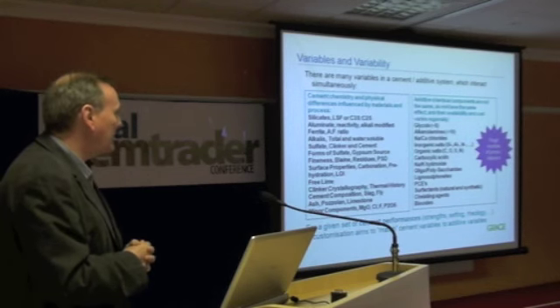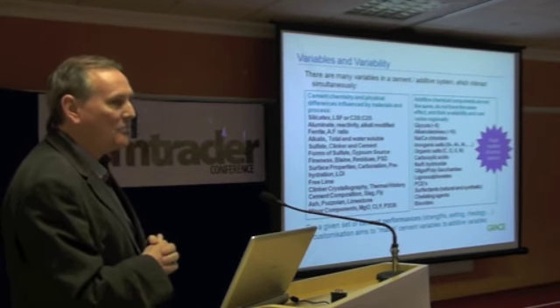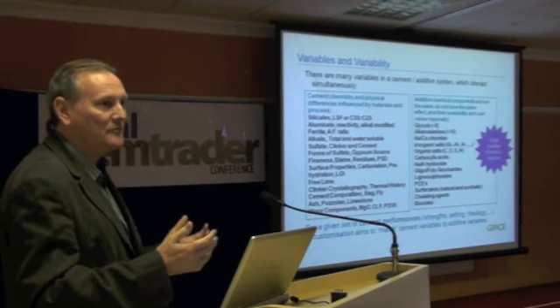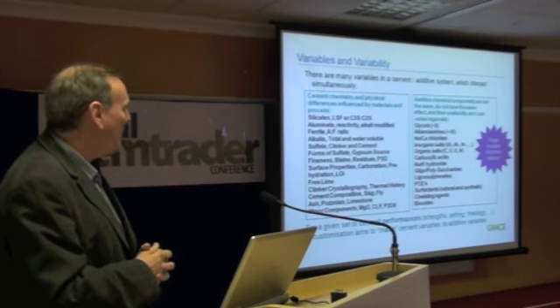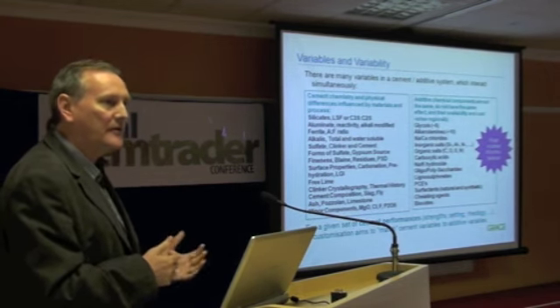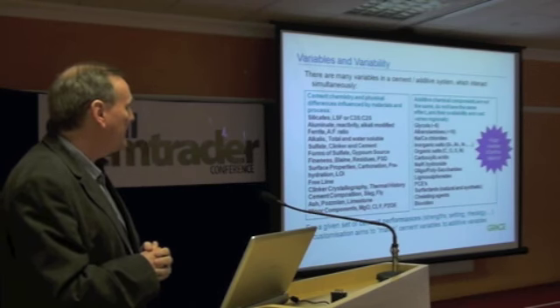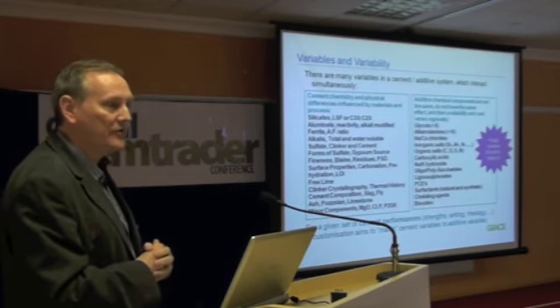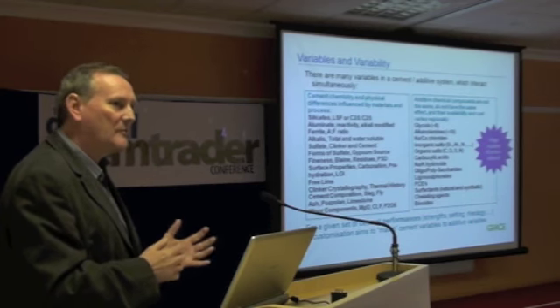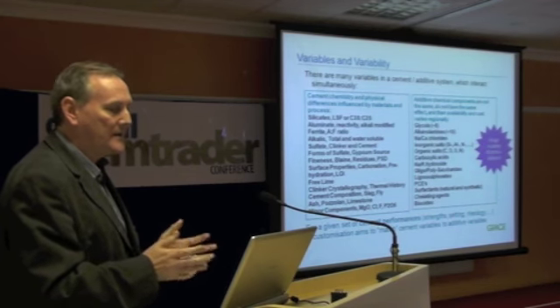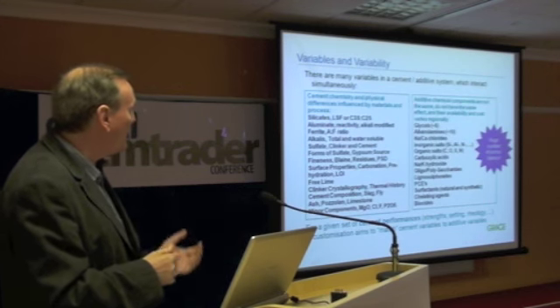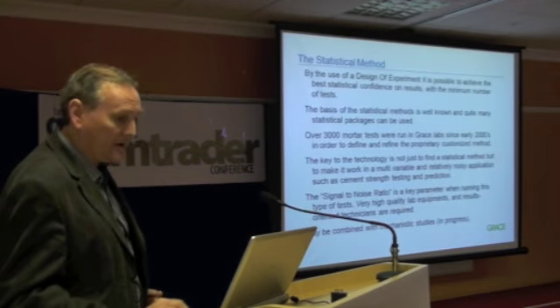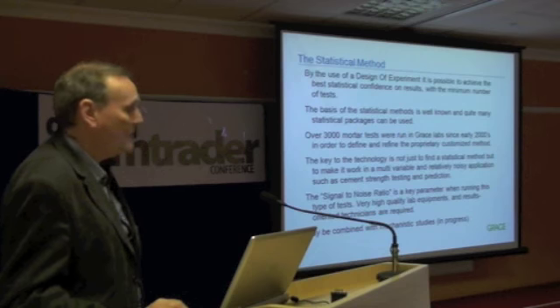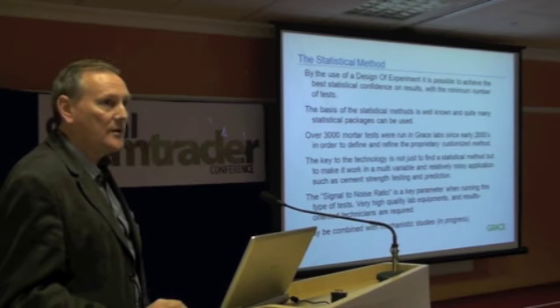So you can say that we have a bit of a practical trial and error approach, which is true to some extent, but combining a lot of experience, about 80 years in doing this, with a lot of more sophisticated statistical approaches, we start putting a little bit of science to it, but at the end of the day, you've still got to do trial and error. So customization, the procedure we're looking at, is really applying a statistical method to be a bit more systematic in looking at the trial and error.